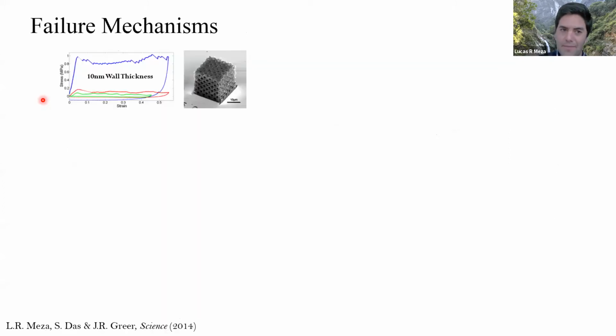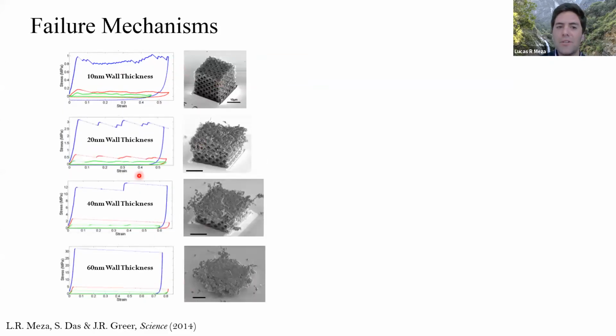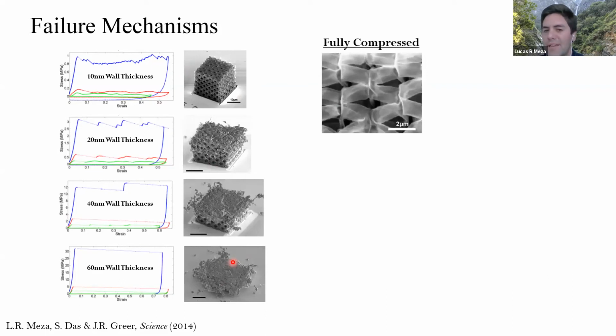So what's happening here? This 10 nanometer one, across all these different unit cell sizes, was able to recover. There's a gradual transition as we increase that wall thickness, from a ductile recoverable behavior to a catastrophic brittle behavior. Fundamentally what's happening is when you compress this thing, you have a hollow, thin shell — imagine trying to crush a piece of paper, it isn't going to fracture, it's going to wrinkle. Here we're actually seeing wrinkling, or shell buckling, in the wall of this hollow ceramic shell.